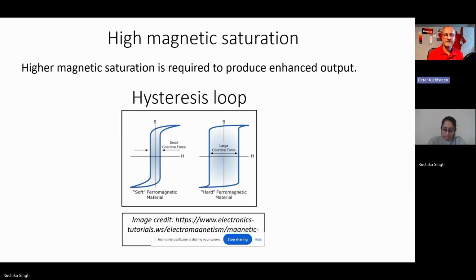Also, this area under this loop is quite thin. If you see the hysteresis curve on the left side, we want that to be as thin as possible, because we want lower hysteresis losses, and you do something to make that thinner. We'll also talk about that. That's exactly what electrical steel is made for, and why they have a thin hysteresis loop. We'll also talk about that.